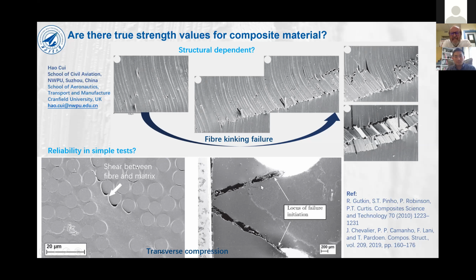on two different tests. The first one is fiber kinking, or the failure of composites in longitudinal compression. And as shown very perfectly here, in a fiber kinking failure, we're trying to measure the strength of the composites in longitudinal compression. And the failure here is normally initiated by the interfiber shear. And this interfiber shear can happen in a unidirectional compression test because of, for example, the misalignment of the fibers against the loading direction.